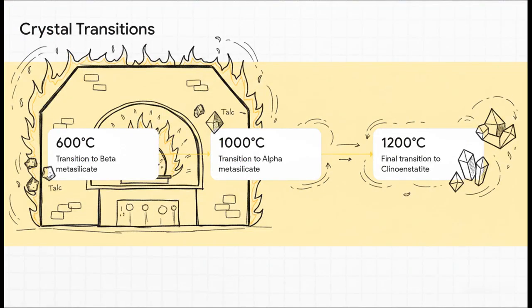Let's look at how this builds as the temperature rises inside the kiln. The heat isn't just baking the material. It's literally forcing the atoms to rearrange themselves. At 600 degrees, the talc transitions into beta metasilicate. Push it to 1,000 degrees and it shifts again, this time into alpha metasilicate. Finally, right around 1,200 degrees, it makes its ultimate transformation into a highly durable crystal called clinoenstatite. The material is fundamentally altering its physical nature, step by step.